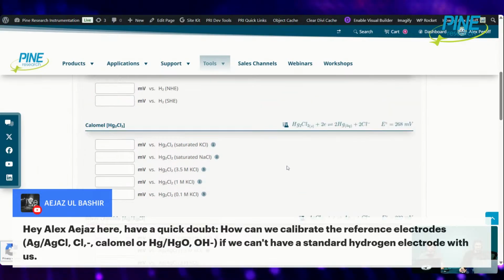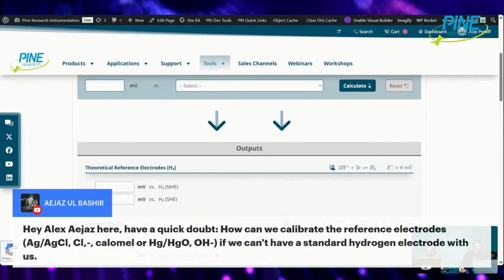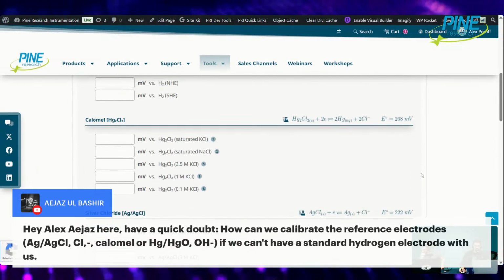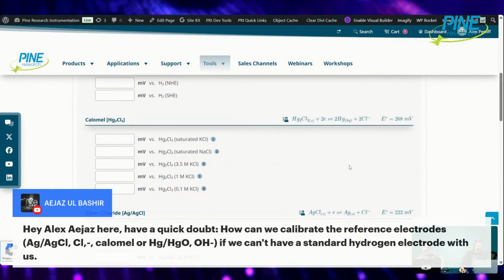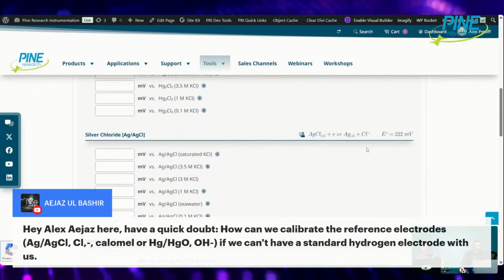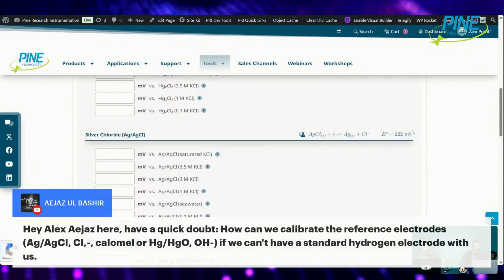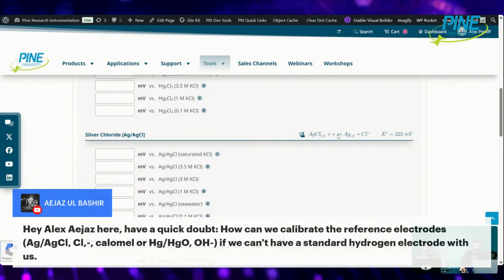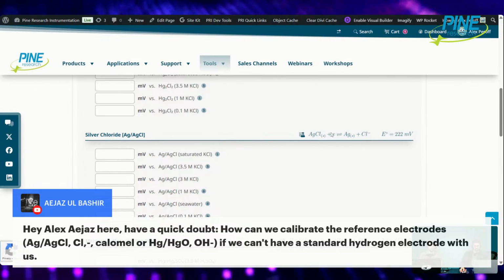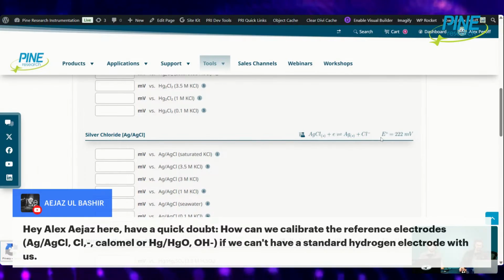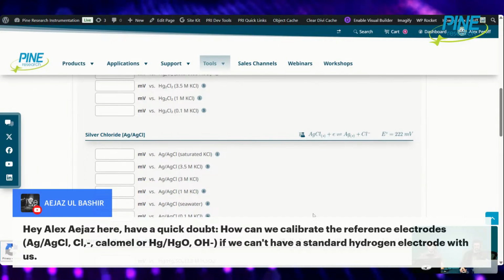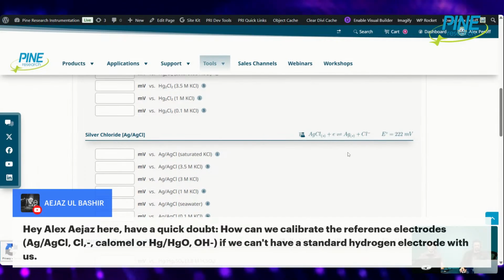But that's the way, if you don't have a standard hydrogen electrode, because this is difficult to create: take two where you know what the literature value is supposed to be, and then compare them. Once you know that you have a good one, you can then take two of the same, like two silver chloride reference electrodes, because you're working in an aqueous chloride environment. You can do that same OCP experiment. The open circuit potential difference between silver chloride and silver chloride is 0. So you should get like 0 or 1, or maybe up to 5 millivolts difference within error. That is a way of determining whether or not your reference electrodes are good.